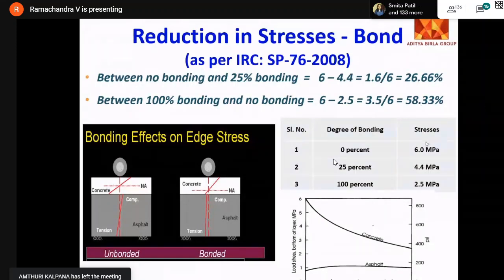Therefore, if there is no bonding, the stress on concrete comes to 6 MPa. And if it is 25% bonding, the stress will come to 4.4, which means 26% less. And if there is 100% bonding, it comes to 2.5 MPa. This is what you are seeing in this graph. The stress in concrete greatly reduces due to consideration of bonding.